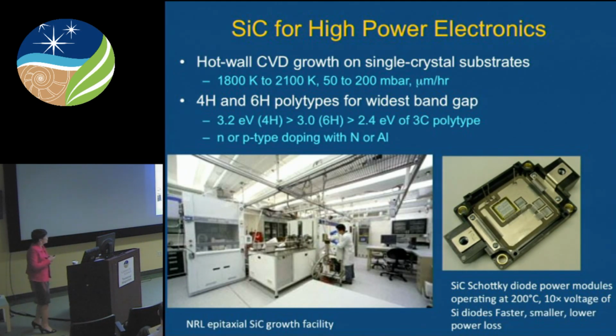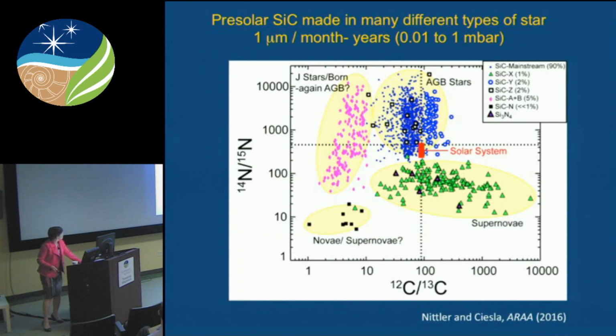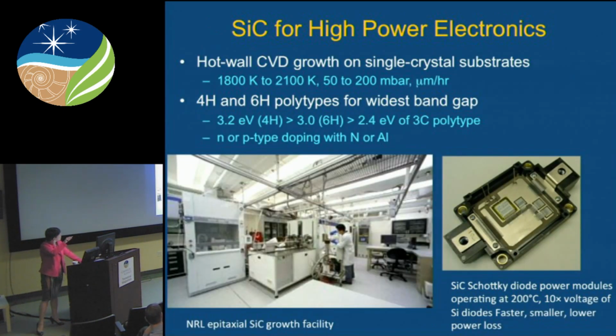Okay, so the industrial applications for silicon carbide include growth. So why would the Naval Research Laboratory have an active area of research in silicon carbide? The Navy needs high power electronics that can work at high temperatures with lower power loss and small dimensions. So we have a very large hot wall CVD growth system, and we focus on the 4H and 6H polytypes, and these are because they have the widest band gap. And so here's an actual NRL silicon carbide Schottky diode power module that can operate at 200 degrees Celsius at 10 times the voltage of standard silicon diodes.